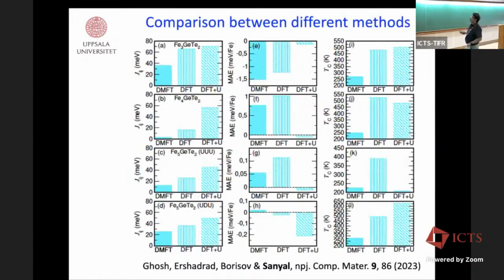I don't have much. Let me come here. This is a comparison between different methods. I talked about the Jijs and the magnetic anisotropy energies. Let's look into this plot here. These are calculated TCs with DMFT, DFT, and DFT plus U. Obviously, DFT gives you a very large overestimation of the Curie temperature here. And DMFT gives you values which are more or less close to the experiments. They're much more renormalized, with much better agreement with the experiments. We can conclude from here that maybe DMFT will be a choice, if possible, to look into these itinerant, not itinerant, localized ferromagnets. I should not call it a purely itinerant ferromagnet.